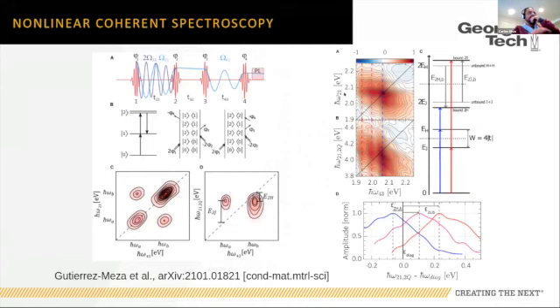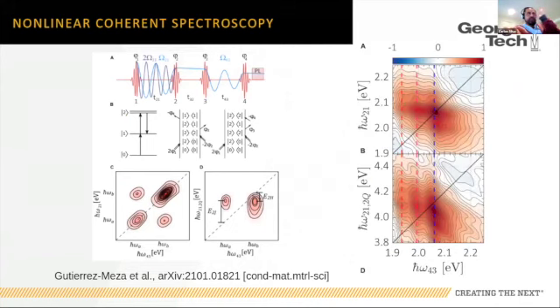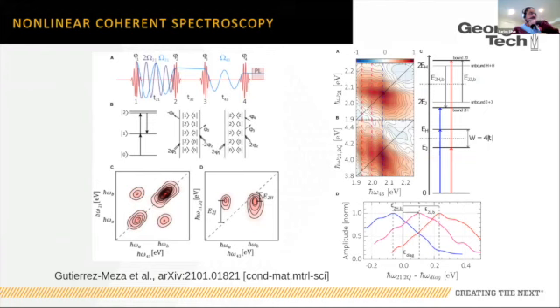So when we look at these correlations, this thing that is at the peak of the 0, 0 of the H aggregate gives us a negative correlation, and normally we would say that sounds like a J aggregate, whereas this thing that we ascribe to a J aggregate, the 0, 0, gives us positive correlations that we normally would ascribe to an H aggregate. So here's this inversion. This is what Frank really likes to call the Jekyll-Hyde aspect of these polymers, that they are hybrid HJ aggregates, and the H-like exciton sees itself as a J-like Biexciton, and the J-like exciton sees itself as an H-like Biexciton. That was something that we didn't expect, but it's something that we would interpret from this data. And I think it follows nicely some of the theory that Eric is going to talk about.